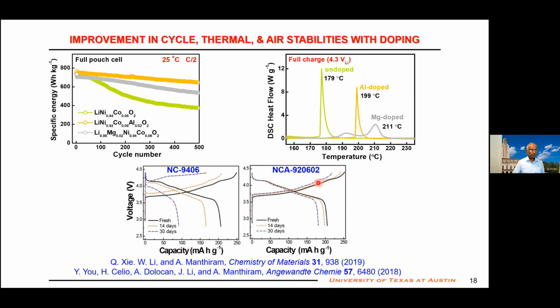Now, it's not only aluminum, many things you can dope. I show 3 here. When we dope with these, they help with all 3 problems. Cycle life improved, thermal stability improved. After storing in air, the capacity retention is also improved. This is amazing. In my life, in science, when you have a problem, you try to fix it, you will make the other problem worse, or you will create a third problem. And here when you dope, all 3 are getting benefited. You are suppressing the challenges with all 3 problems.